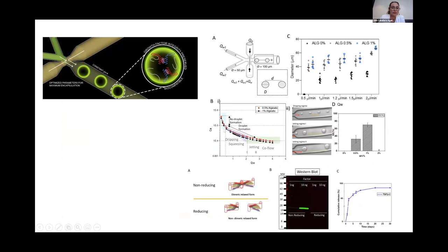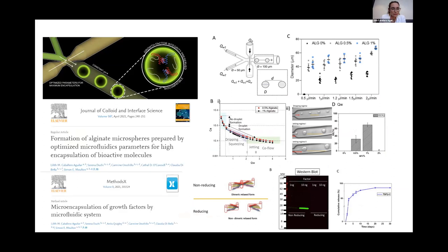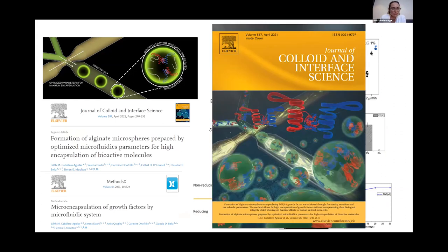We did a lot of characterization on the encapsulation of the growth factors. We showed that the growth factors were still in their integral form. So basically they were still active after the encapsulation and in the release. And we published all this characterization in the Journal of Colloid and Interface Science. We also got an inside journal cover, and we also published a method in Methods X. So by that time, my PhD was coming to an end, basically. But all the knowledge that we acquired really continued to be used during my postdoc project.